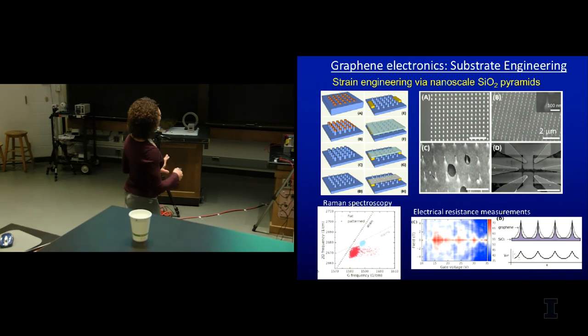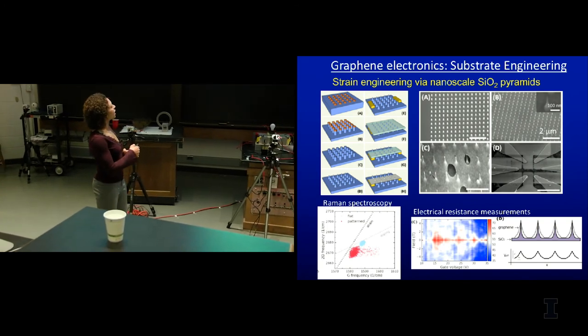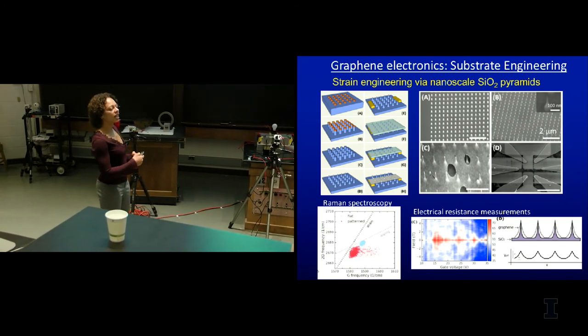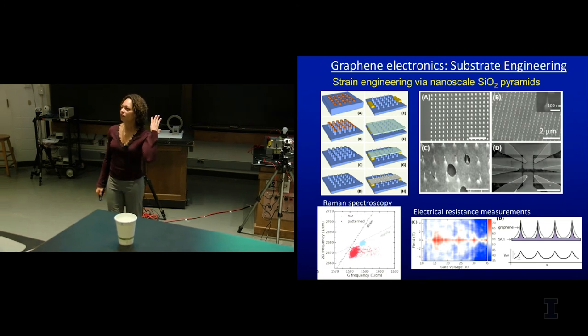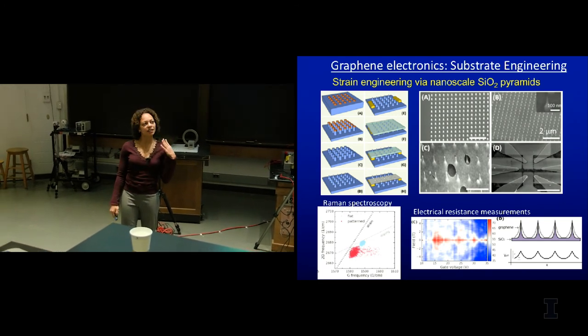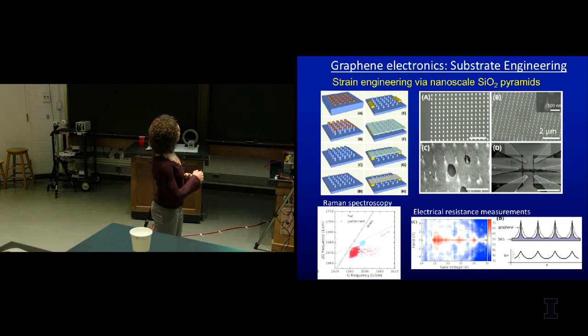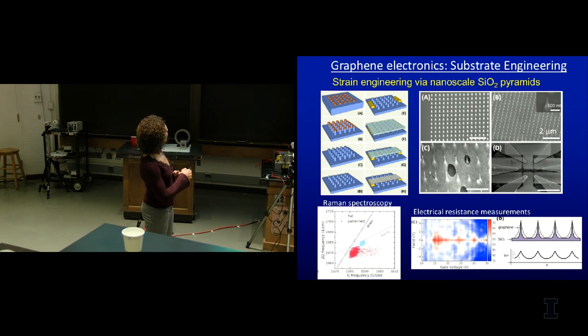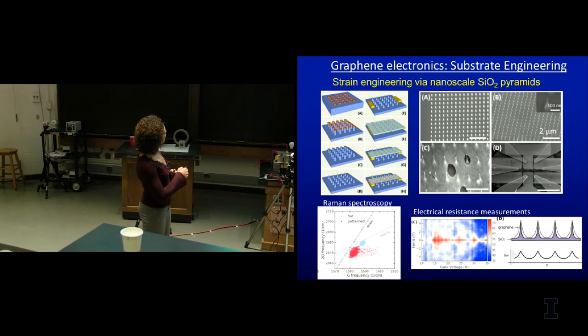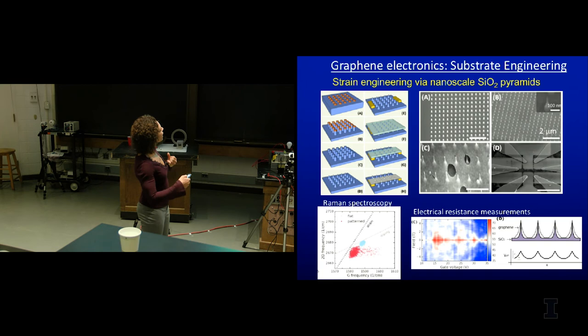I'm not going to go into detail about what we measured, but here we just scattered light. We hit the graphene with light and looked at how it reflected off. And depending on how the light reflects, it tells you about how much it's strained. You get different shifts in the frequency of light when it's strained versus when it's not strained, if that makes sense. And so you can see these blobs, these little things tell you that when it's not strained, you get one frequency of light, and when it is strained, you get another frequency of light, which shows that we are straining it just by getting it to adhere to the top of these pyramids.